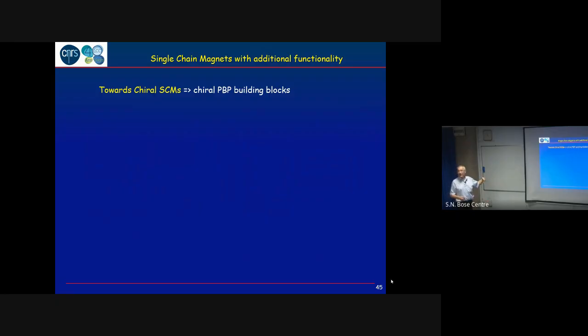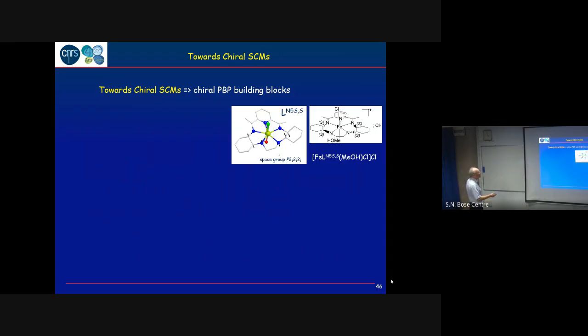But what I would like to show you is how the chemist can control the synthesis of a chiral single chain magnet. Of course, if you want to control chirality, you have to play with chiral systems. And this means you are going to use a chiral building block. So here is an example of a molecule we are using. We use a pentagonal ligand that is very similar to the ones I've shown before. The difference here is that the ligand is chiral. So we have introduced here and here chiral centers. And so we can do the synthesis with one enantiomer, so we control the chirality. So here is one of the substructures of one of the complexes that has been made with the ligand that has SS stereochemistry, that is shown here.